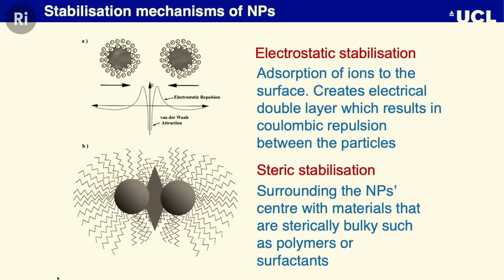So you need to have an electrostatic repulsion, so they have enough charge that they are separated apart. But that's not stable when you're adding acid, because you change the charge, or you add salt electrolyte. So you need to have another stability mechanism. They call it steric stabilization. So you either use a big molecule like a protein or polymer. That's something to keep them apart, so they are stable.